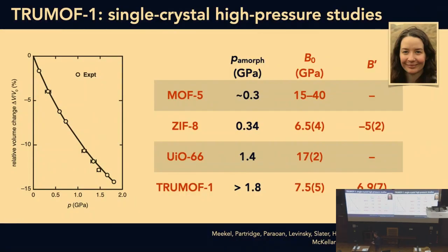So we've just done the obvious experiment with it, which is that you take that system and you squeeze it, like we squeezed our things before. And when we had something that was periodic and like a wine rack, we squeeze it and it gets longer. This thing is disordered. It has the symmetry of a cube. So when you squeeze it, it has no option but to get shorter in every direction. But the thing that turns out to be very weird about it, and it doesn't sound very exciting to start with, is that when you squeeze it, you can keep squeezing it. It just keeps getting smaller and smaller.